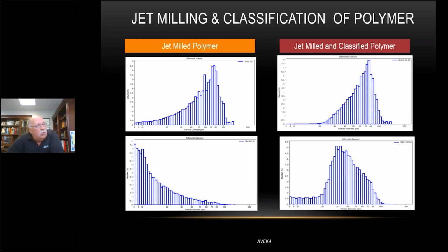So instead of looking at the volume in each one of these bins, we were looking at the number of particles. I do want to point out, in deference to HORIBA for setting this up, all these particle size distributions that I'm providing here were done on our HORIBA systems. If you don't have a HORIBA, please buy one, they're great. But the issue here is that if I had one 100 micron particle and I were to break it up into 1 micron particles, I would take that one particle and make 1 million particles out of it. It's an incredible change. You can see that even though we have the big volume in the size that we want, the number of particles in the fines is just incredible.